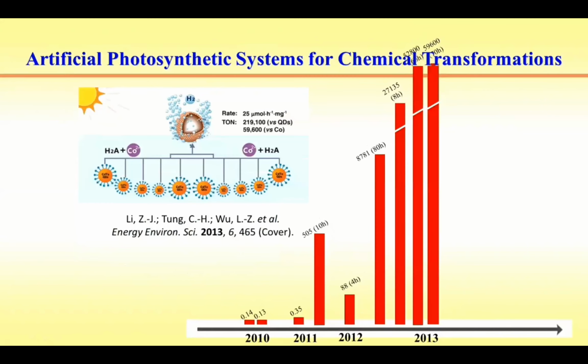Learning from nature, we are very much interested in designing an artificial photocatalyst that is abundant, stable, efficient, and sustainable. Here are the examples. We discovered a simple artificial catalyst that is made only from a photosensitizer and an abundant cobalt salt under visible light irradiation in water. Upon irradiation, the generated photocatalyst is able to produce hydrogen from water with turnover numbers of 220,000 at room temperature. And this kind of catalyst is quite stable and can be reused many times without losing activity.